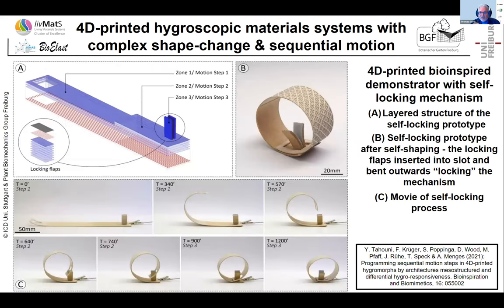And the soft machine should do the following. You have here a strip of 4D printed material with a hole on top, and you have 2 lashes on the base. And the idea is that the basal part of this strip remains more or less straight. If humidity is given, this is the dry state, this part remains more or less straight. This part curls in, and curls in a way that the opening goes over the two lashes, and then with a given time delay, the two lashes bend outwards and lock it. So you have a self-locking mechanism with a three-phase motion, exactly as we have seen in the silver thistle.